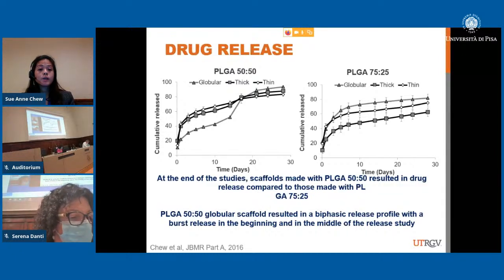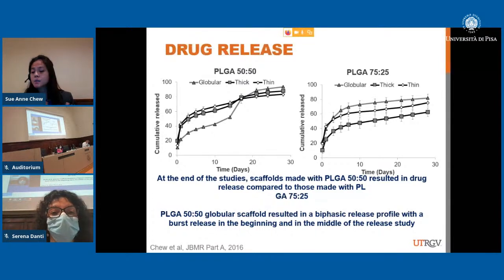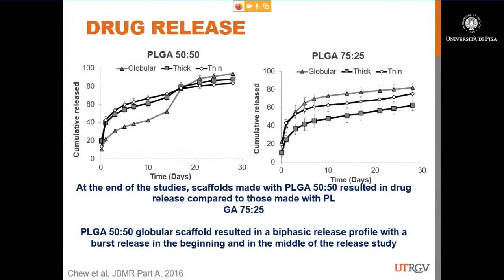And at the 50-50, we were able to see a biphasic release profile, right? It was a small burst release in the beginning, which is expected for scaffolds, right? But in the middle, we see another burst release. So it was based on how that scaffold was degrading and the morphology changes that we see that second burst release. Again, we saw that the surface volume ratio was not the only thing controlling the drug release. It was also tied to the degradation of the scaffold, right? So it was not a clear-cut understanding of how it happens, but it's a mixture of both of these, the degradation and this surface volume ratio.